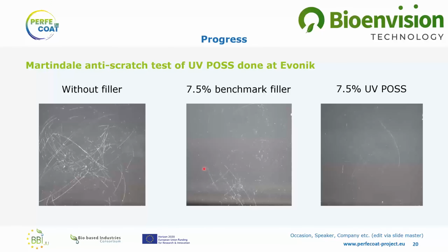Next here was the testing of mechanical strength using UV POSS. UV POSS was put into the coating, and the coating was placed onto a substrate, and the Martindale anti-scratch test was done on it. The first picture shows a coating without any filler, and the second one shows coating with the 7.5% benchmark filler, while the last one is 7.5% UV POSS used as a filler.